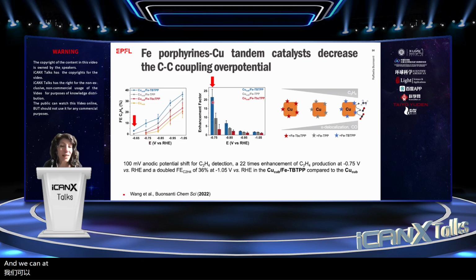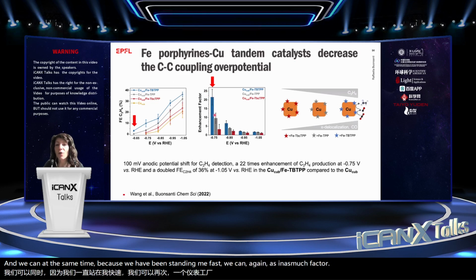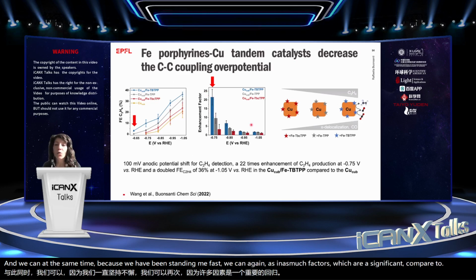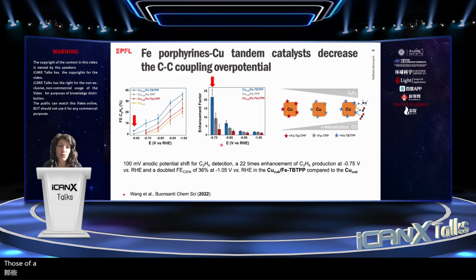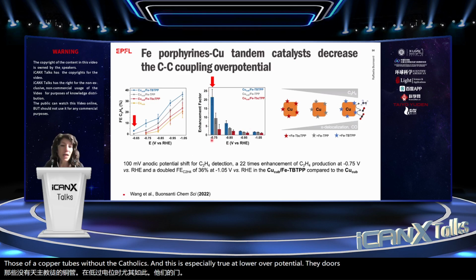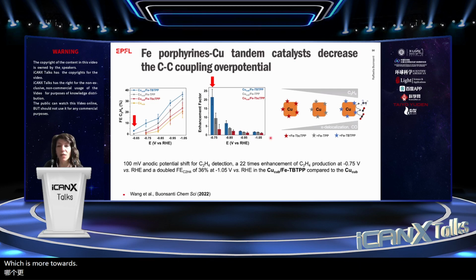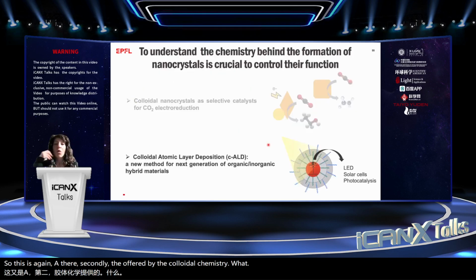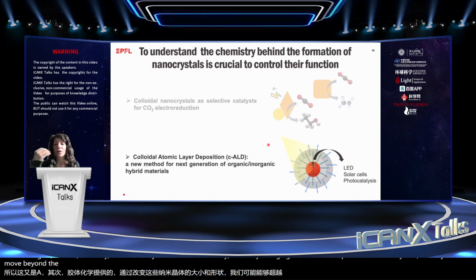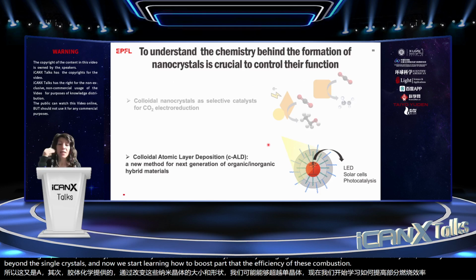And at the same time, because we have this tandem effect, we can again have enhancement factors which are significant compared to those of the copper cubes without the catalyst. And this is especially true at lower overpotentials than those that we normally work with, which is more towards minus 1.1 volt versus RHE. So this is again the versatility offered by the colloidal chemistry, where by changing the size and shape of these nanocrystals, we were able to move beyond single crystals. And now we start learning how to boost further the efficiency of this conversion and the selectivity by combining copper